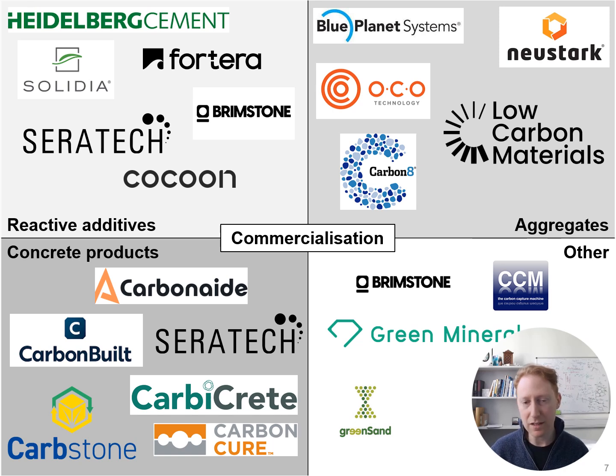So we can apply CO₂ mineralization to produce reactive additives in concrete. That's what is shown in the top left of this slide. And that is, for example, clinker, cement, and clinker substitutes. On the top right, I show companies that are producing aggregates, and these aggregates can be dense or lightweight. On the bottom left, I show companies that are producing carbonated concrete products like blocks, bricks, or pavers. And then there are other products that are outside the concrete value chain, which I show on the bottom right, and we won't focus more on those in this presentation.